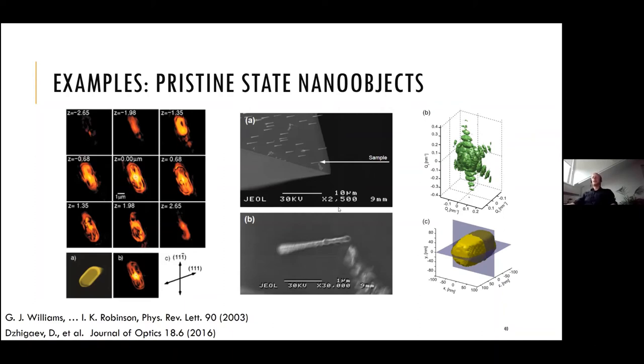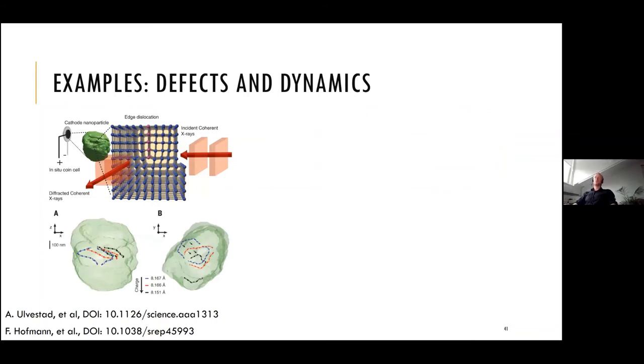More recently, work was published on single nano-objects in the field of nanowires, nanocomposites, or different artificially made nanostructures, where you can access the strain fields during the growth or some influences of the growth approaches. One important example is that you can study defects and their dynamics in real, applied materials like battery cathodes, which also consist of nanoparticles. You can access how dislocations inside the particle nucleate and propagate during charge and discharge. So it's actually in a functioning device.